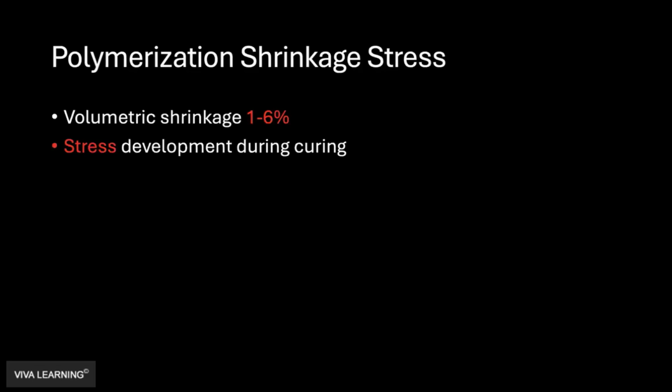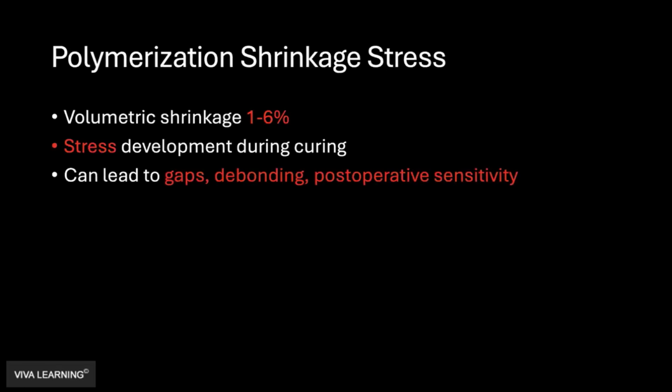And this stress is basically developed when you cure the composite and it turns from the more pasty type of liquid form to the hard form. All those molecules organize in such a way that it makes the composite become smaller. And this is what causes debonding, postoperative sensitivity, and all the things where the patient comes in saying, hey, my composite is sensitive. Ever since you touched that tooth, my tooth has been sensitive. All of these problems that you don't want to have probably could be eliminated if you follow protocol properly.